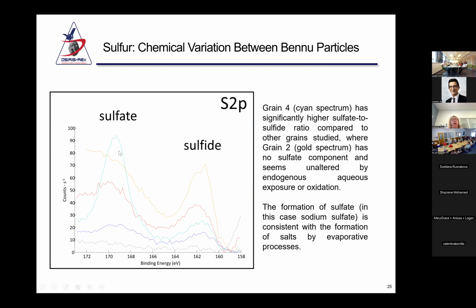We can tell whether the sulfur on the surface is chemically a sulfate or a sulfide. I'm sorry that these are hard to see, but we see in a number of particles that the sample surface has been preserved as a sulfide, but there are other surfaces like the cyan here where it's predominantly a sulfate. And because all of these samples were processed in the same way, we know this must be endogenous to the planetary surface. So what is this telling us at this moment? The formation of sulfate is consistent with the formation of salts by different types of evaporative processes: ponds inside the planetary parent body that evaporated over time, leaving behind these types of salts.